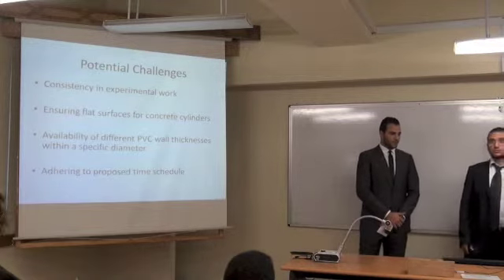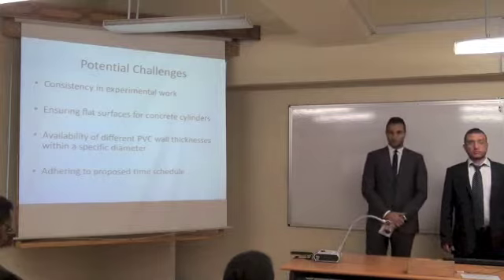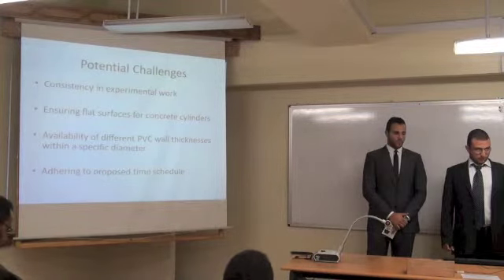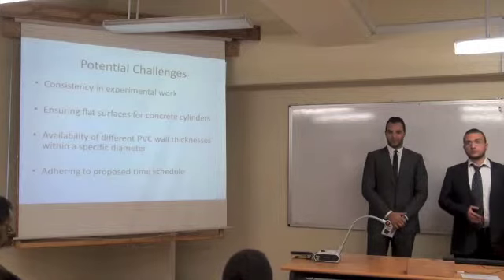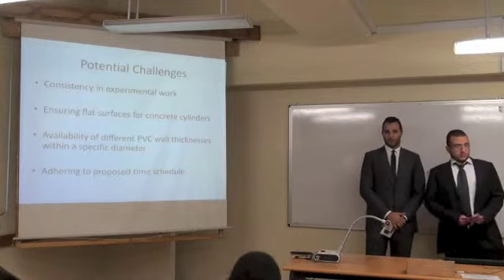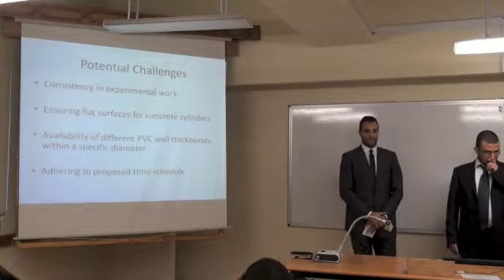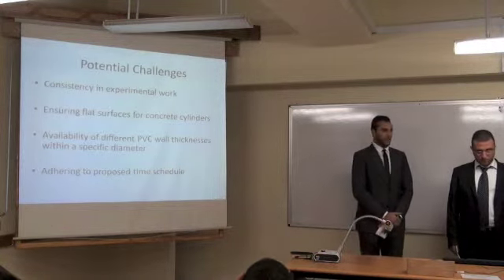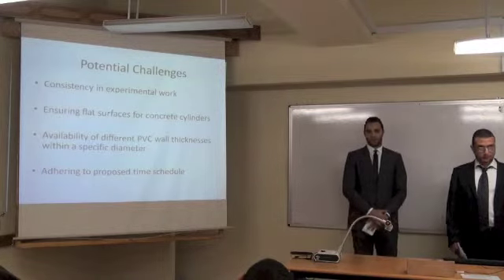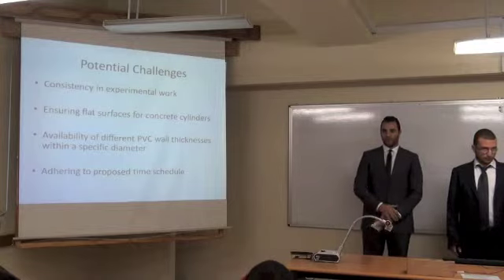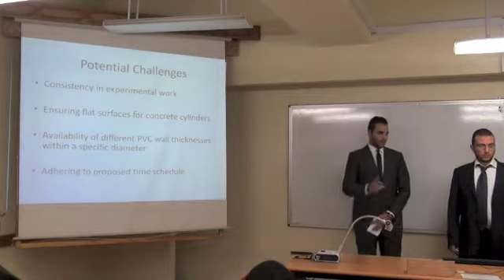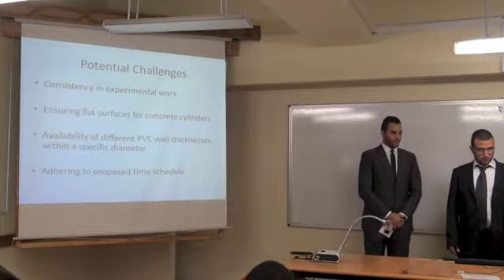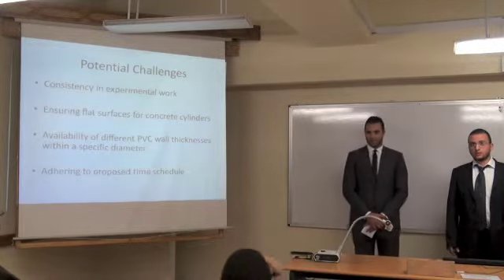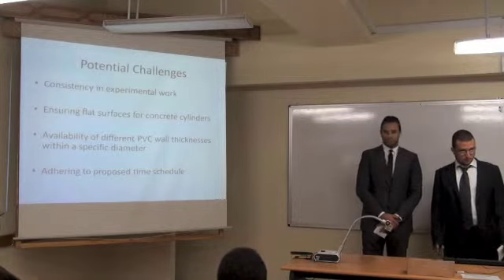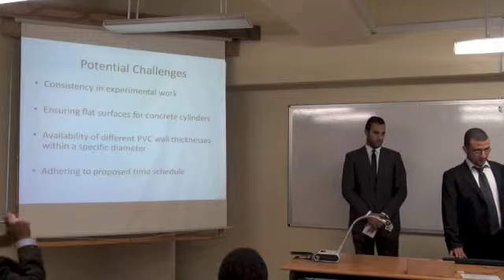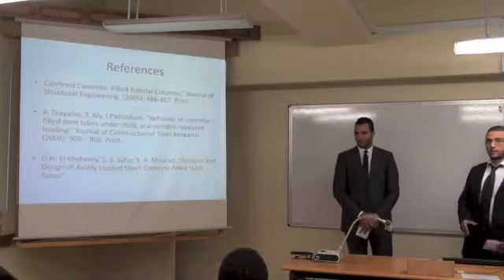Our potential challenges are the consistency in experimental work, which is how to apply the tests on many different specimens, and we have like 54 types of columns, short, medium, and long, with different diameters, different thicknesses. We also are aiming to ensure flat surfaces for concrete cylinders, as I said before, to be flat from upward. Also, the availability of different PVC wall thicknesses within a specific diameter. And last thing is adhering to the proposed time schedule to be on time to finish the testing. These are the references. Thank you.